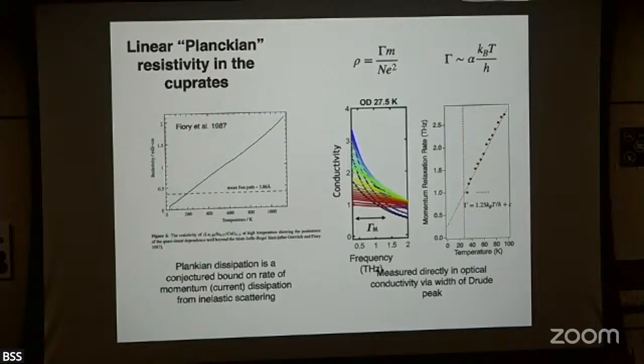And you do, at temperatures well above the Debye temperature or the Bloch-Gruneisen temperature. What is difficult to understand is, you can certainly come up with various temperature regions which will give you linear T resistivity, but how you could come up with one mechanism which will pass the baton from 40 Kelvin all the way up to 1200 Kelvin without changing the slope. That's harder to understand, right? We also need a very, very low Bloch-Gruneisen temperature. People have argued that you can get this with phonons. I think the recent data that I'll talk about, also what my student Will, who's here, is working on, shows that this picture of phonons doesn't work.